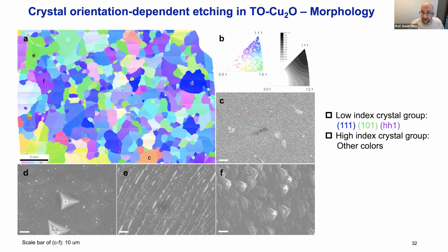And so, for instance, it's mainly low index crystal groups oriented, where these numbers are low, 0 or 1. And we can see nicely that, for instance, D here, this we expect where we have this cube with the edge poking down. And in fact, we see in our SEM that we have this triangular pit. This effect gives rise to this different optical effect where you can then see it with your naked eye. Essentially, we can see with our naked eye the orientation of the different crystals due to this differential etching. And so here with the E, this is the 101, so it's like the crystal has been rotated up like this, and then with the F, it's rotated up like that. So that's very nice and interesting.